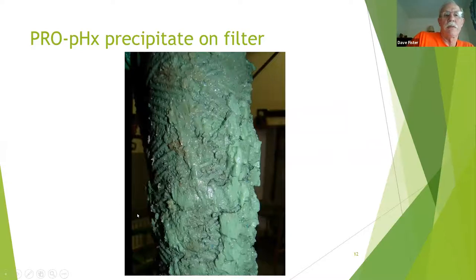So this is what the PRO-pHx precipitate on a filter looks like. This happens to be a spiral wound filter, and the green crud is a mixture of organics and the metal silicates. I've seen the spun cartridge type filters where you can actually wipe off the sludge and keep reusing the cartridge for at least a few more cycles. And the fiber spiral wound, maybe not. But the whole point is what you're disposing of in terms of hazardous material is cartridges or sludge that you've wiped off the cartridges. There is no wastewater to be treated.